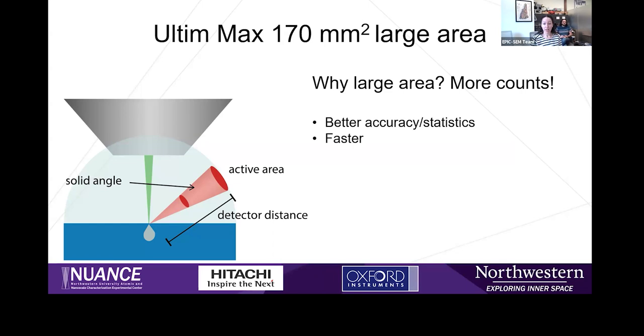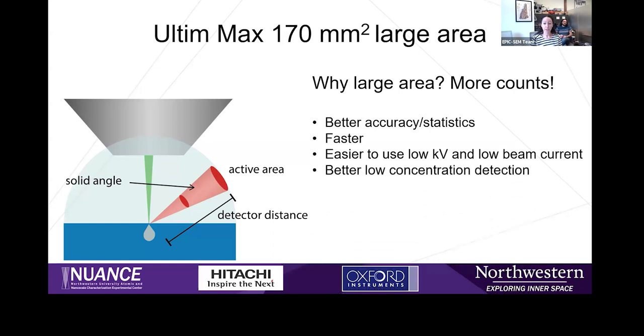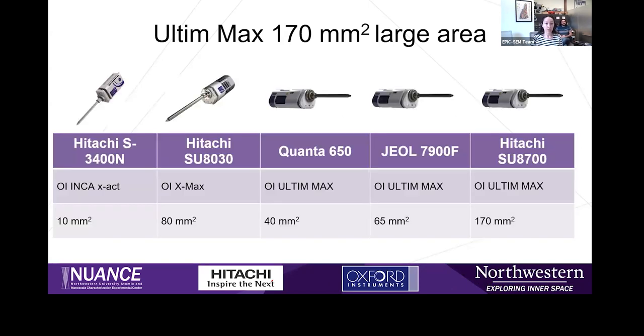It's faster. It means you'll also get better data in situations that before you might have had very low count rates. Things like if you're using a low kV accelerating voltage or low beam current, maybe if you're trying to increase your spatial resolution or prevent sample damage. More counts also means it's easier to detect low concentration elements and also light elements if they're needed. This detector is rated with a detection range down to beryllium.